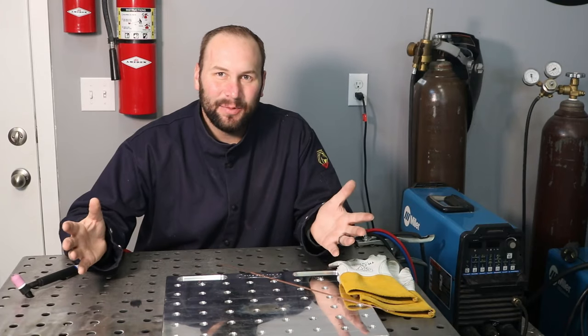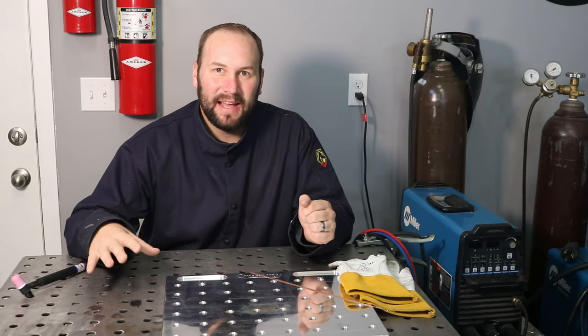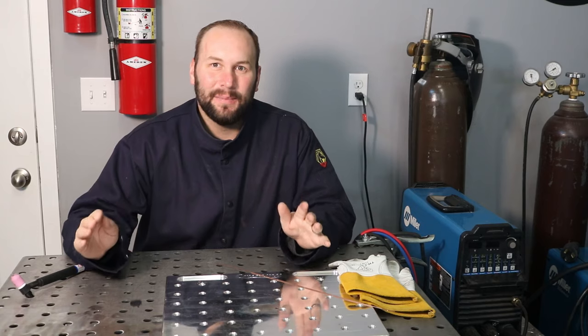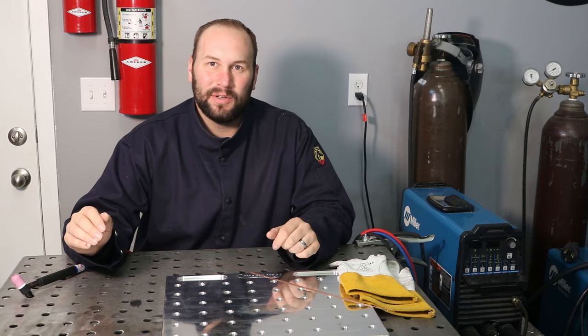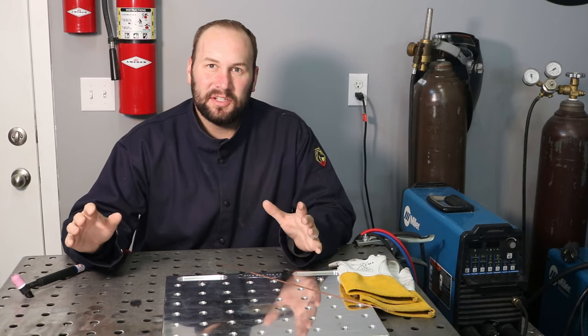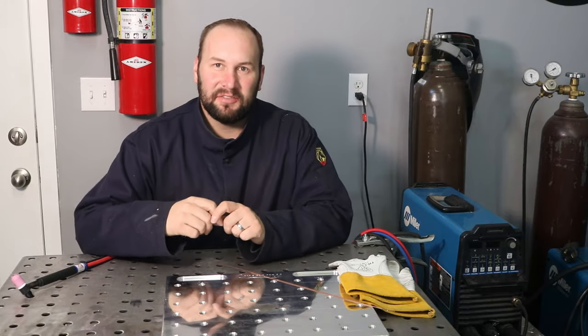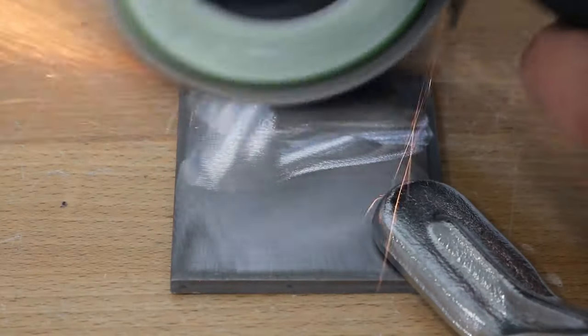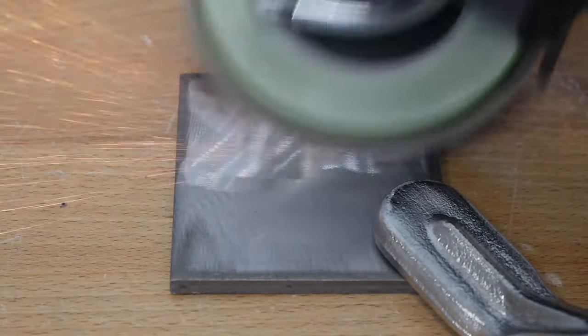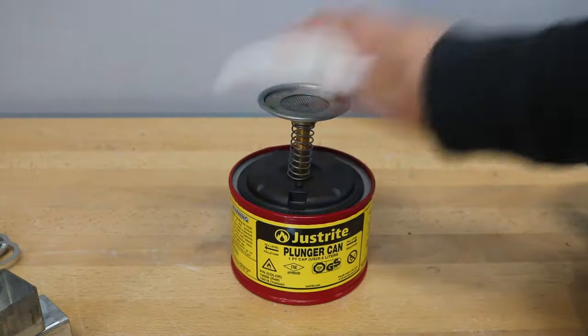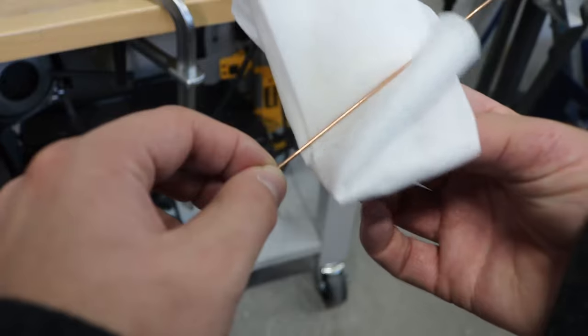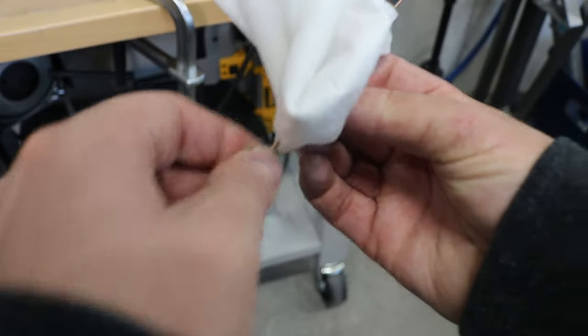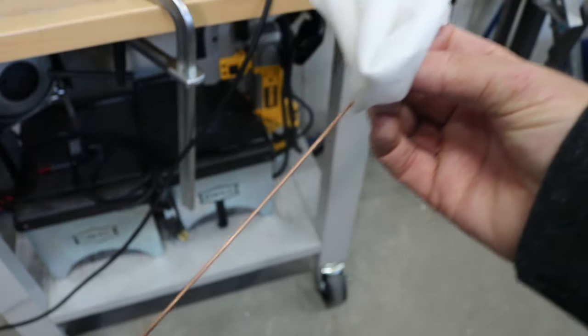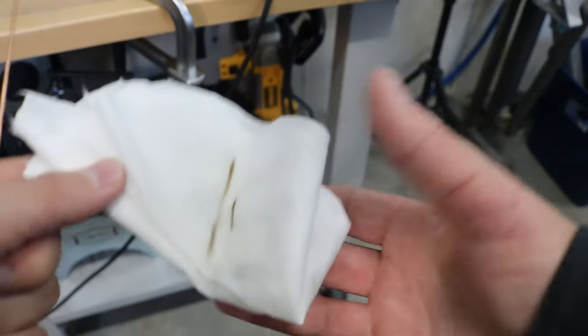Okay, so we got our gear, we got our machine, we're set up here at the station. Let's talk about getting set up, and then we'll get into welding technique. So when you're setting up, the first thing to do is make sure you have clean material. So I'll go ahead and grind off any mill scale if I have it on steel, and then take a rag, soak it with acetone, and then wipe any residue off of there. I'll also take and wrap that rag around my filler metal and pull it across to make sure it's nice and clean, because that'll give you a much better result.